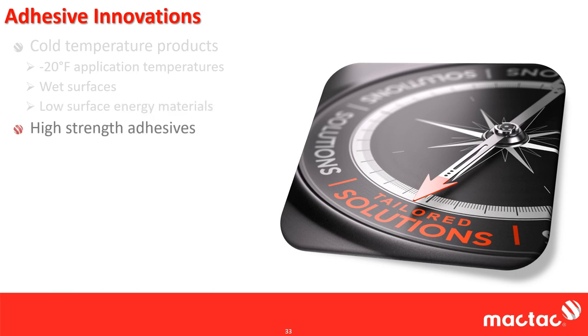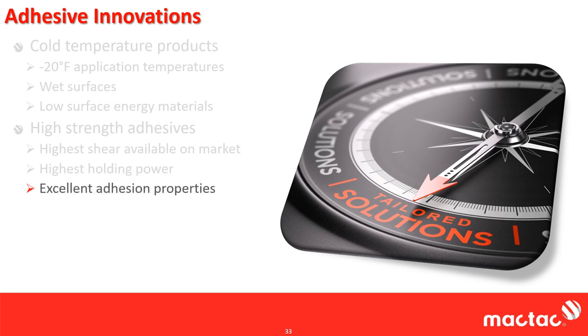We've also created a line of high strength adhesives. These adhesives offer the highest shear available on the market and the best holding power. In order to measure the strength of these products, we had to use 10 times the weight normally used in these types of evaluations. This PSA offers the closest properties to a structural adhesive than any other PSA on the market. And not only is it super strong, it's also got excellent adhesion properties to a wide range of substrates, including low surface energy materials.